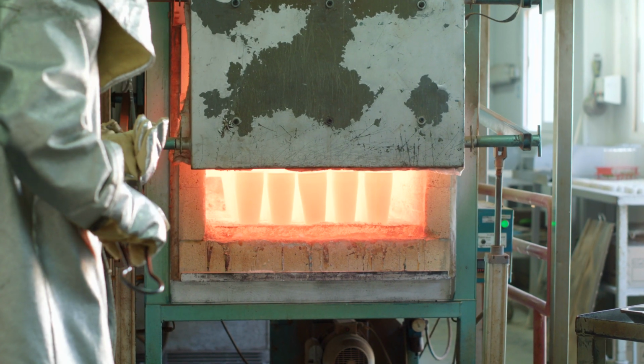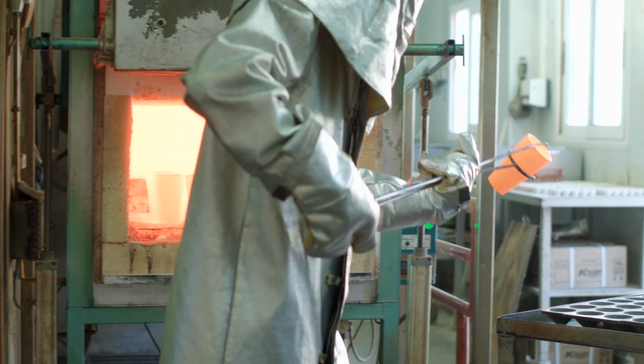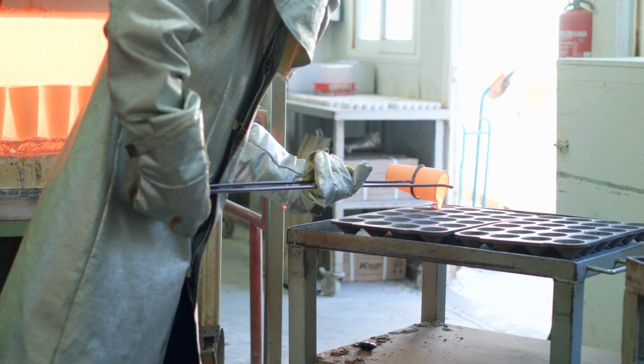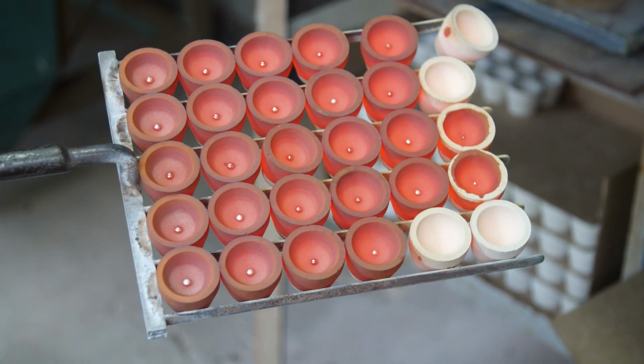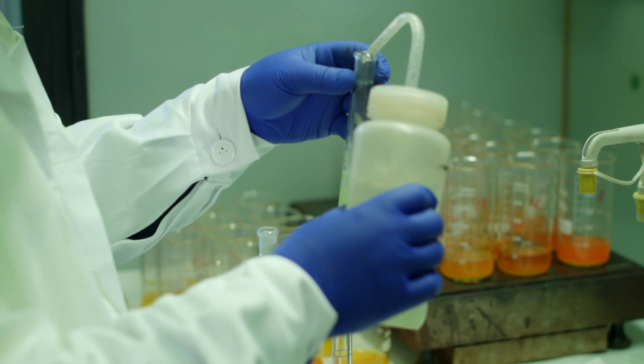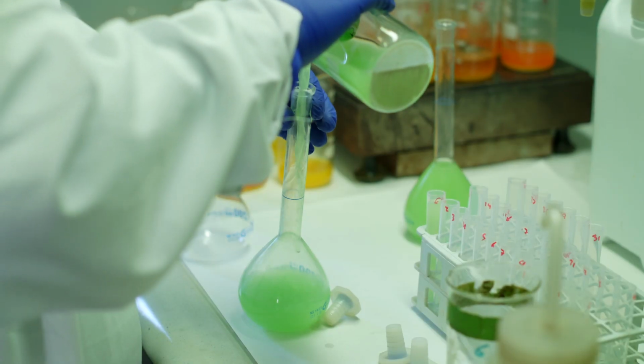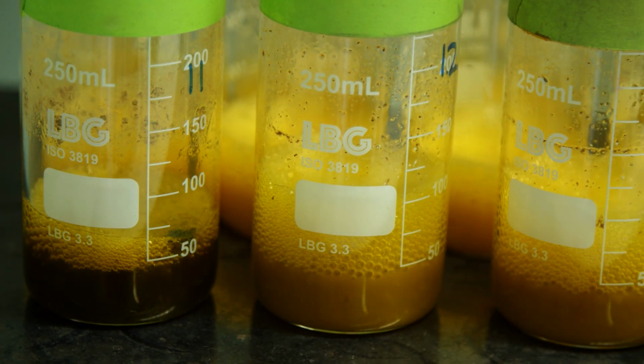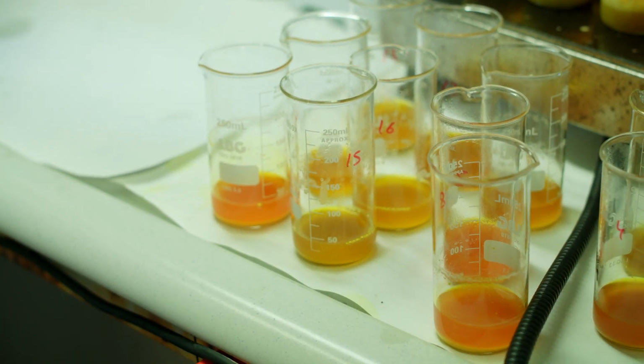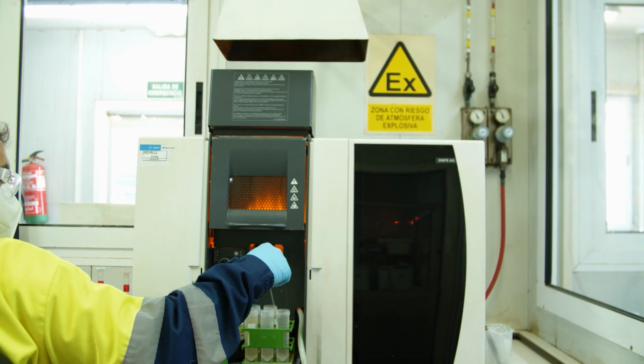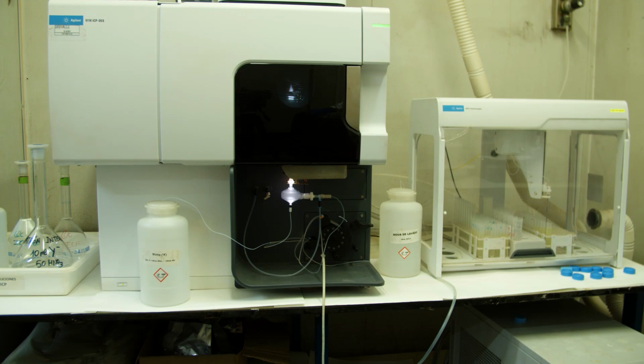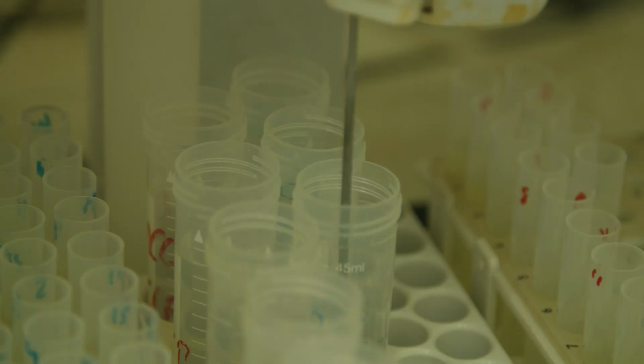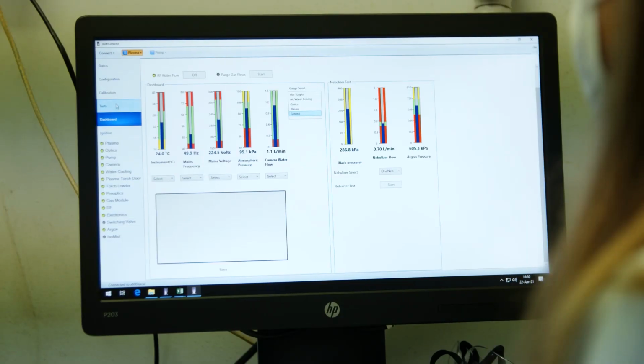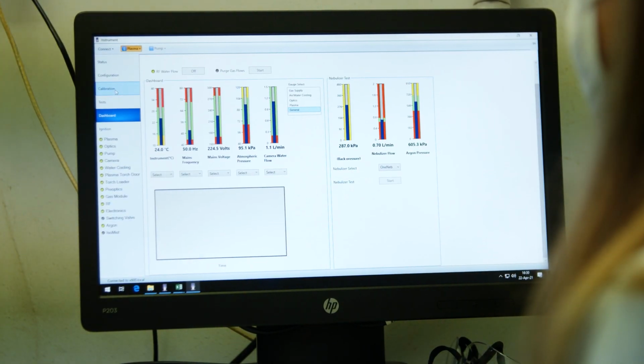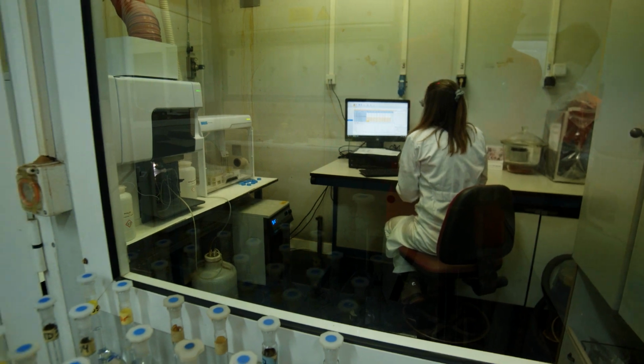Then they go to the laboratory where, following two procedures known as fire assay and acid digestion, they disintegrate and remain in solution. Finally, in the dissolved liquid samples, the content of metals of value such as gold, silver, and copper can be measured. These measurements are made using optical spectroscopic analysis equipment, atomic absorption, and ICP. As a general rule, in each sample we analyze between 7 and 12 different chemical elements.